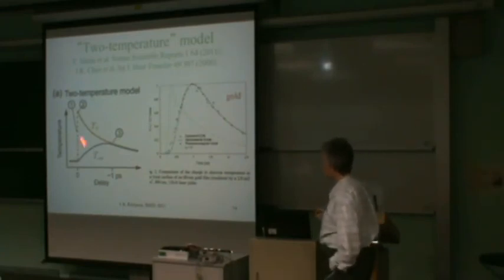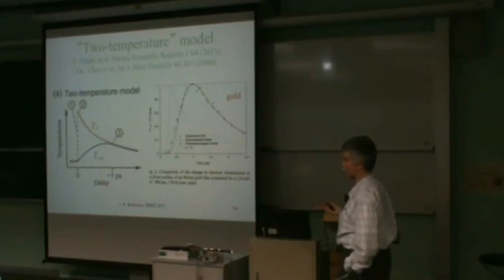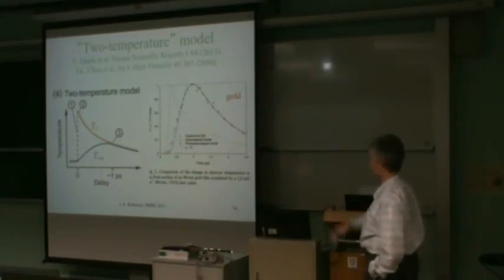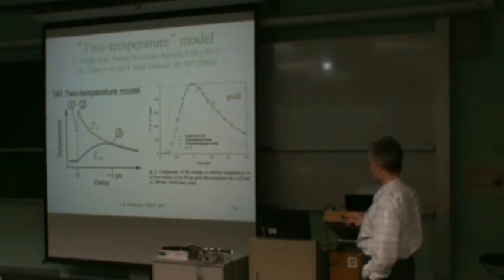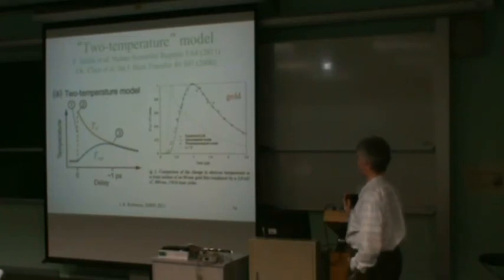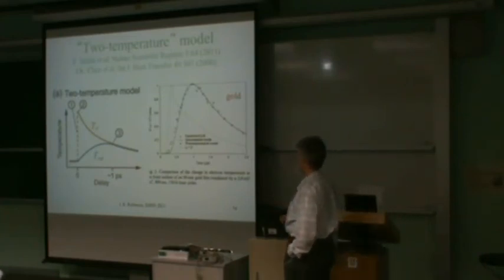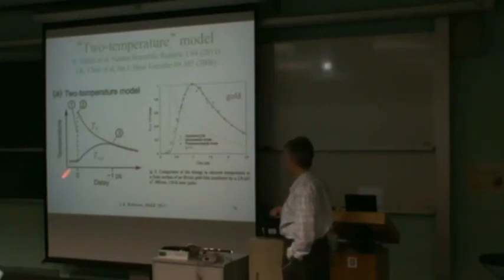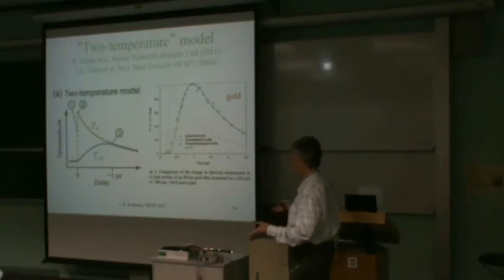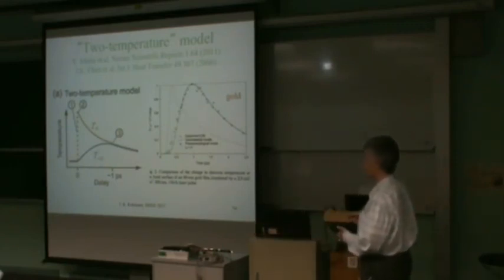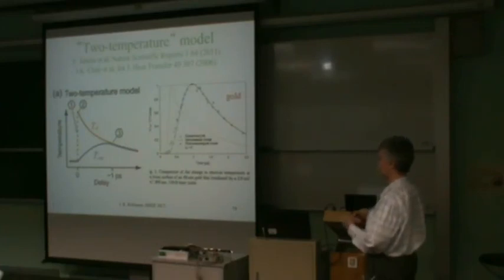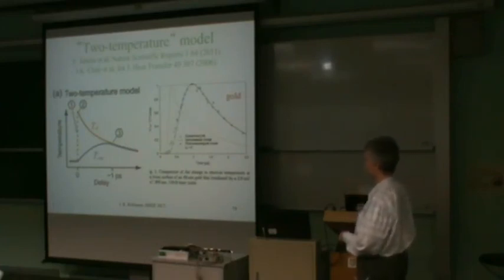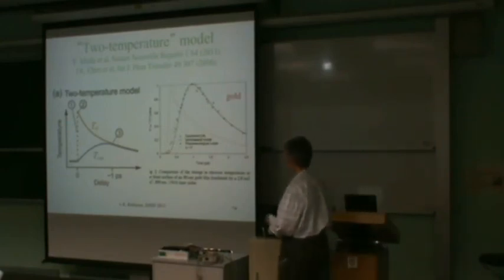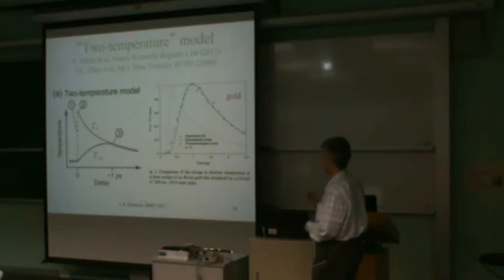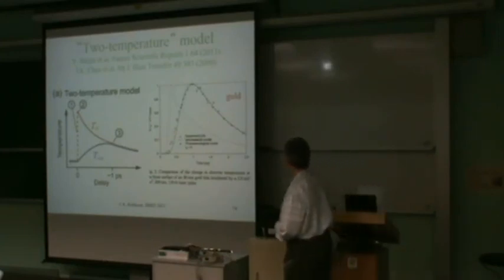And that's believed to take place on the timescale of about 1 picosecond, much less than the oscillation period that we're seeing. But more importantly, because you excite the electrons first, the electrons can travel very fast through the crystal, and even though the light is absorbed inside the skin depth, the electrons travel right through the crystal, and by the time they transfer their energy to the lattice, they've already completely filled the crystal. And so we get uniform heating, as far as we know, of the crystal by the electrons that are generated by the laser hitting on one side of the crystal. And this two-temperature model is fairly well established for laser heating of metals.